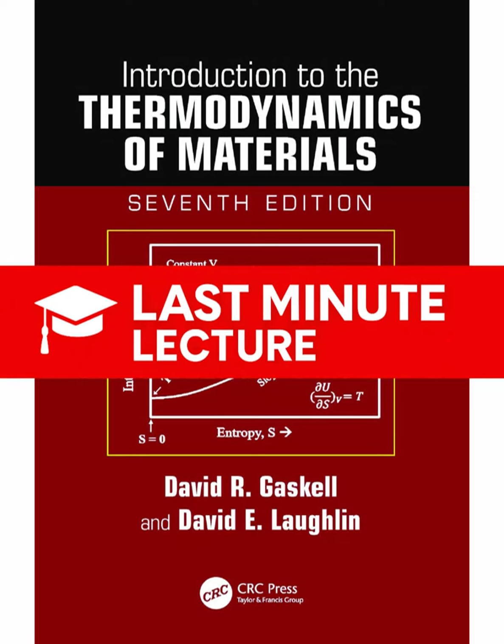And then Planck and Simon took the final step, stating the third law as we know it now. Which is? The entropy, S, of any homogeneous substance in, and this is the key phrase, in complete internal equilibrium is zero at 0 K. That qualification, complete internal equilibrium, sounds like it's doing a lot of work there. It is paramount. Everything hinges on it.